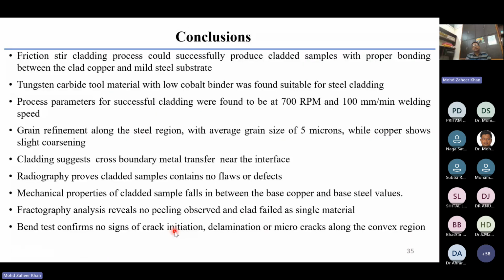So as a conclusion, we can say that friction stir cladding process can successfully produce cladded samples with proper bonding between the clad copper and mild steel substrate. Tungsten carbide tool material with low cobalt binder was found to be more suitable for the steel cladding operation. Process parameters for successfully cladding was found to be 700 RPM and 100 millimeters per minute.